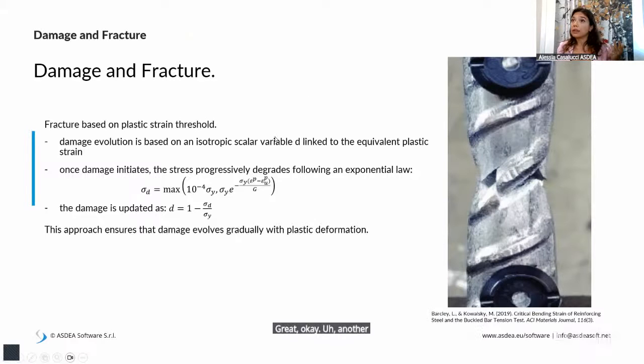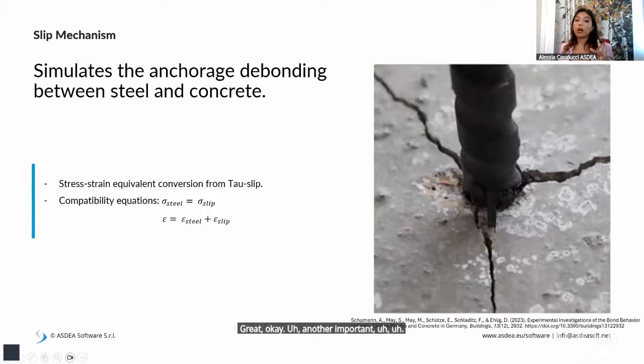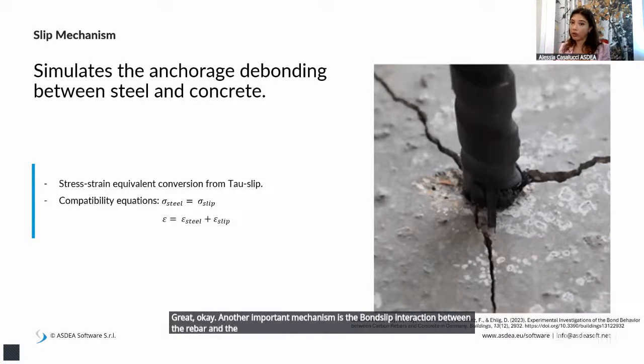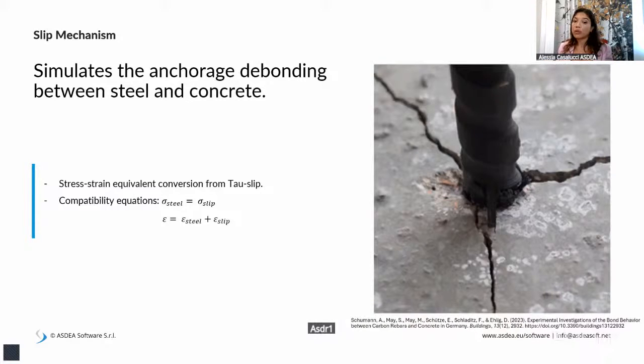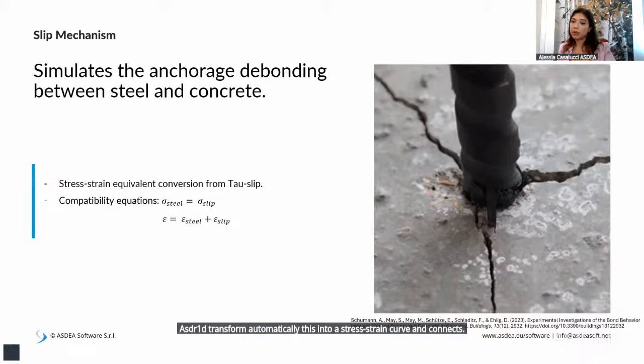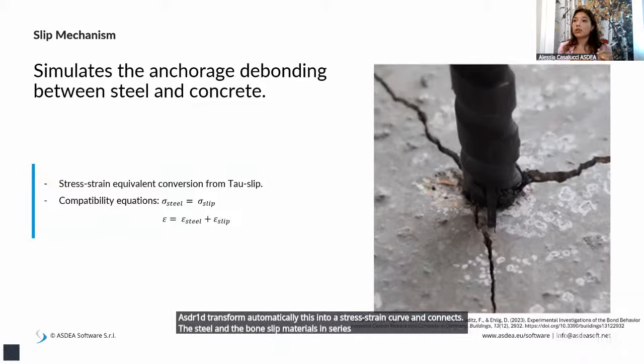Another important mechanism is the bond slip interaction between the rebar and the surrounding concrete. In our model, the user can choose any external uniaxial material to define the bond slip law, usually as a tau slip curve. Internally, the ASDSteel1D automatically transforms this into a stress strain curve and connects the steel and the bond slip materials in series. This ensures stress continuity and strain compatibility.